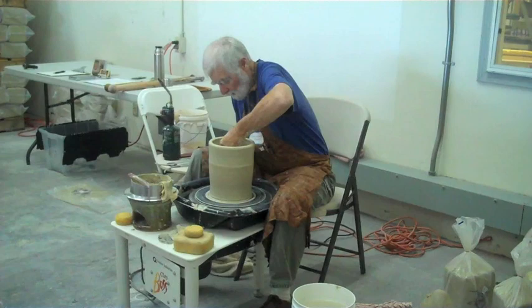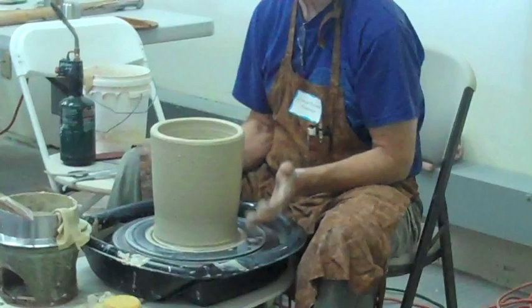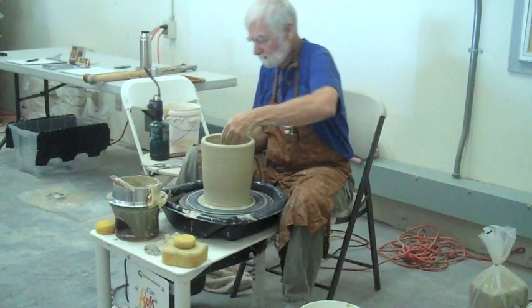One thing to keep in mind is that when you're lifting clay, what's happening? It's moving upward, but what's happening internally? Anybody? Well, when you're lifting clay, you're separating the clay platelets. If you look under an electron microscope, clay platelets kind of look like a contact lens, but kind of oval. And they slide within each other and out. So what you want to do, especially on larger pieces and even small pieces, is to rib down.